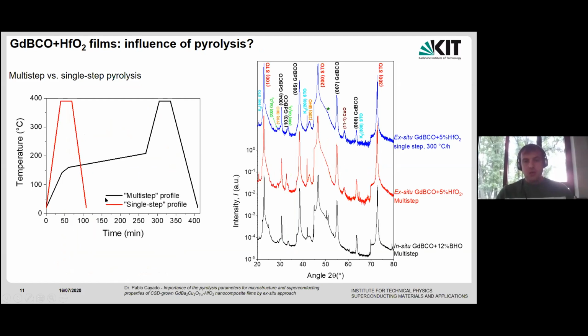And when we use this other pyrolysis profile, called the single step profile, which is much shorter and reaches the same temperature but much faster, because we avoid these long intermediate steps, we observe that we could reduce a lot or even totally avoid the presence of this 103 peak. So there are no misoriented grains, or at least they are very reduced, while we also observe nice and intense 00L peaks. So this gave us a hint about the importance of the pyrolysis process, something that was never thought of before.